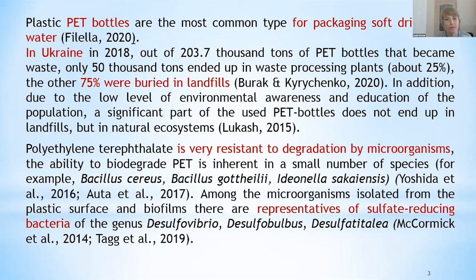In addition, due to the low level of environmental awareness and education of the population, a significant part of the used PET bottles does not end up in landfills, but in natural ecosystems. Polyethylene terephthalate is very resistant to degradation by microorganisms. The ability to degrade PET is inherent in a small number of species, for example, Bacillus cereus, Bacillus gottheilii, Ideonella sakaiensis. Among the microorganisms isolated from the plastic surface and biofilms, there are representatives of sulfate-reducing bacteria of the genus Desulfovibrio, Desulfobulbus, Desulfatitalea.